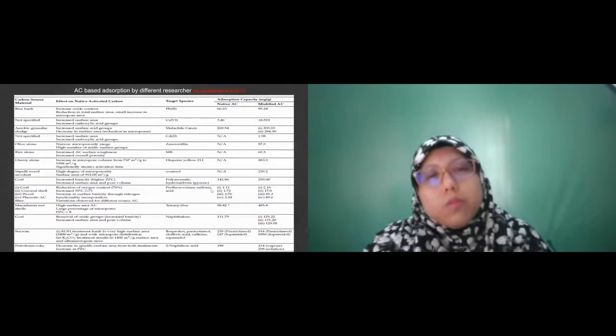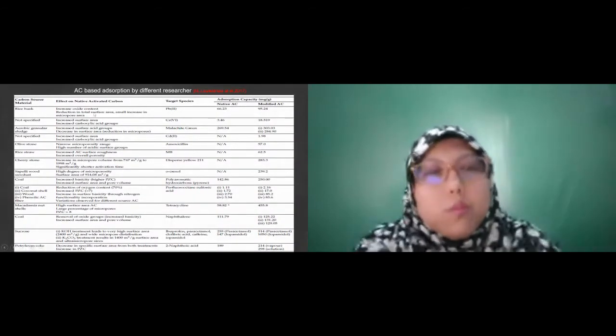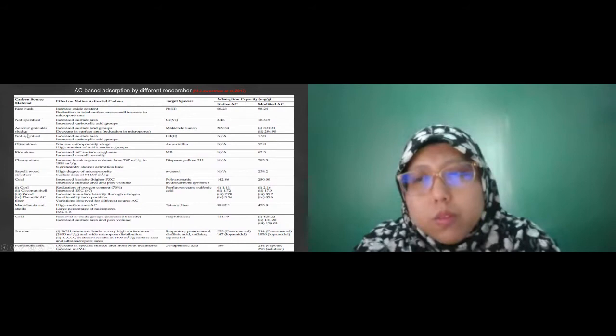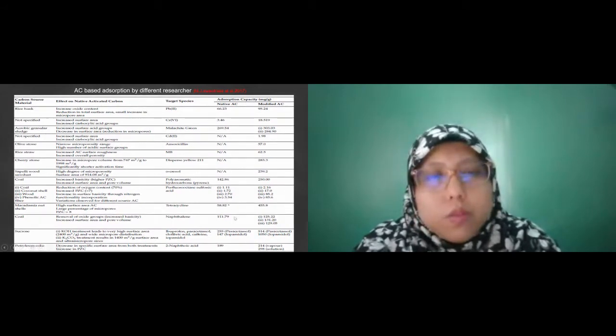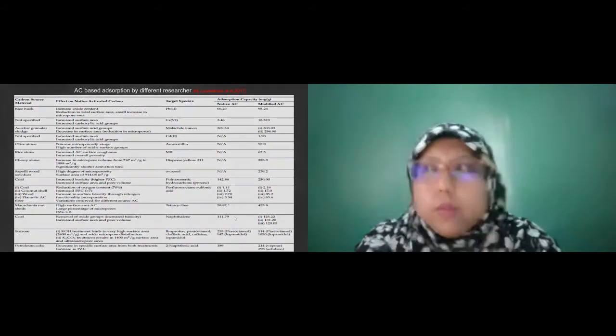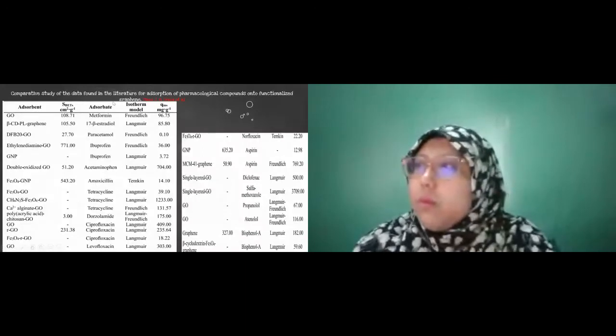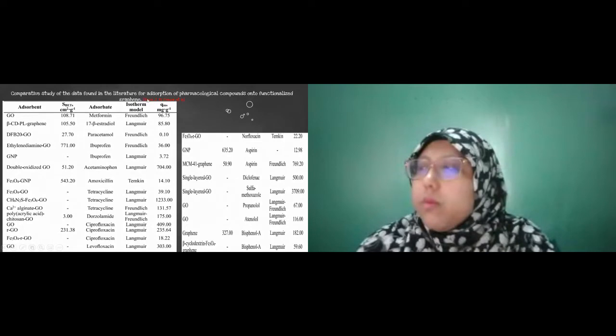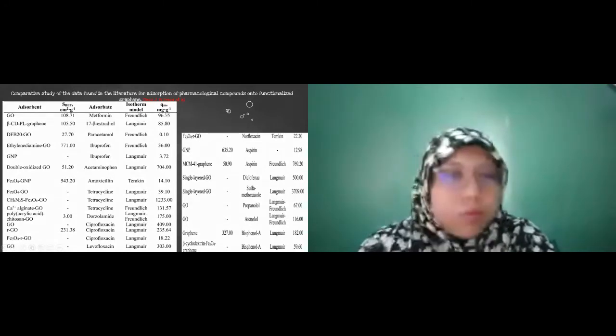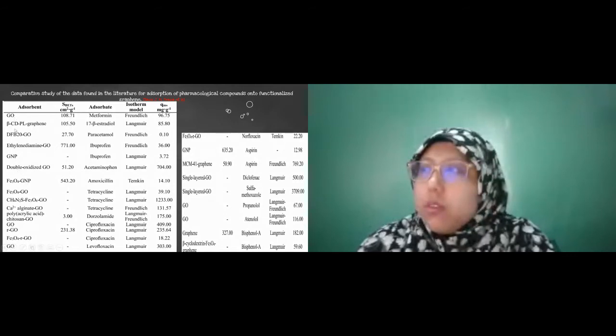That's why if we go through the literature, we can see that almost every available lignocellulosic biomass has been turned to carbon, and we have got very good adsorption capacity. Like rice husk gives good results, granular sludge also gives good results, nutshells give good results. So these all have been used for adsorption. And here we see the adsorption by functional graphene, mainly for the antibiotics, is also very good. Graphene oxide, and graphene composites with other catalysts, all are giving good results.